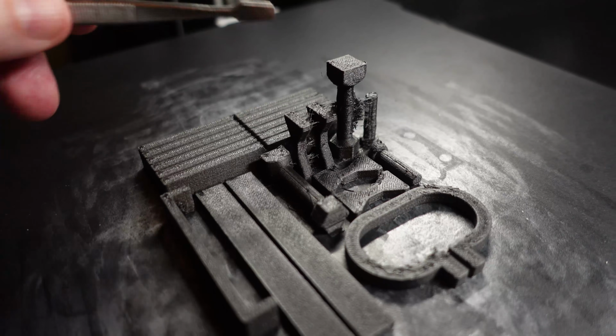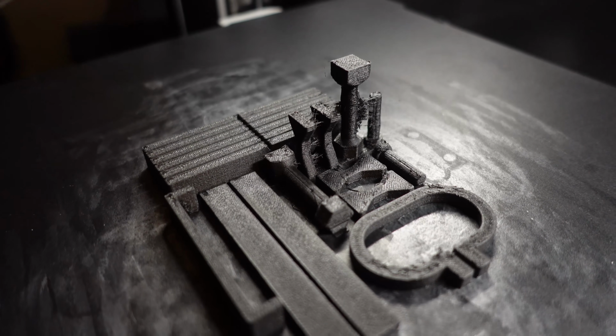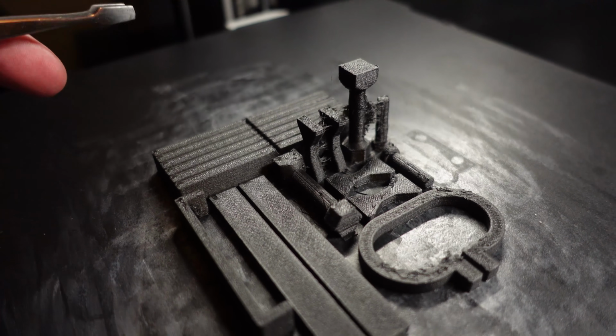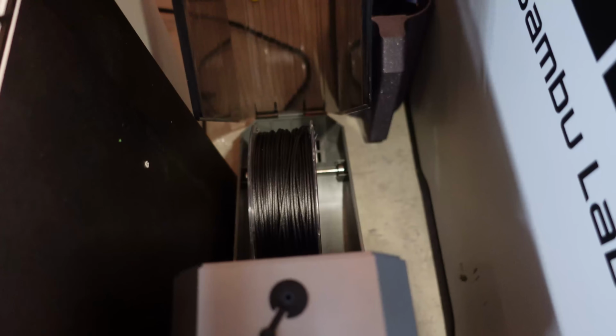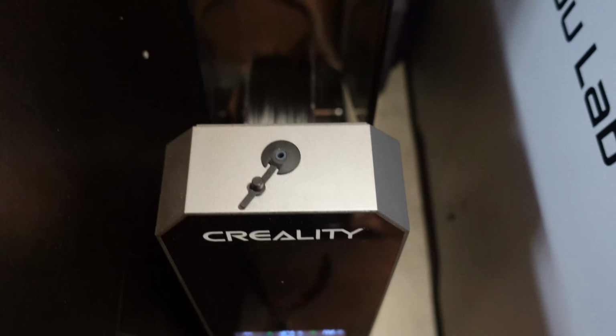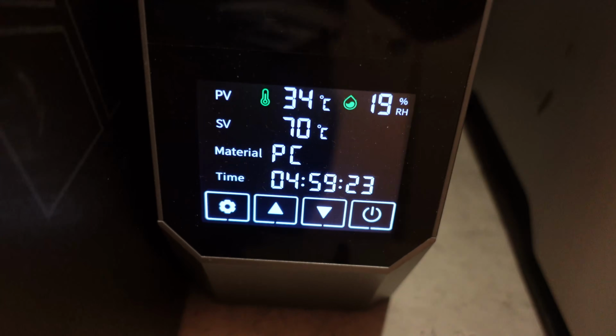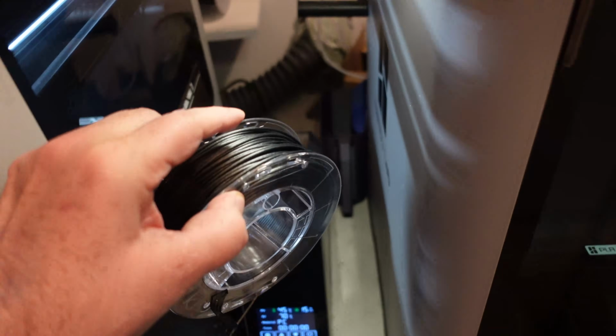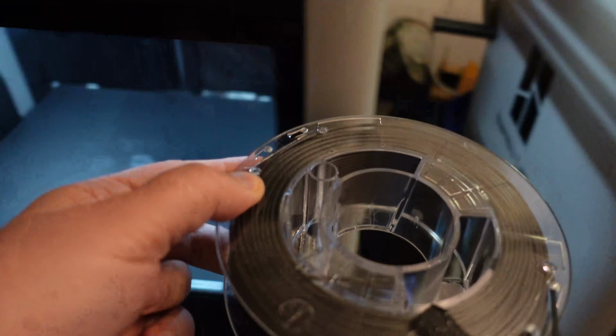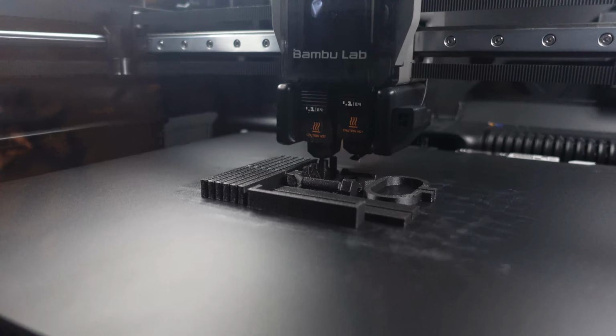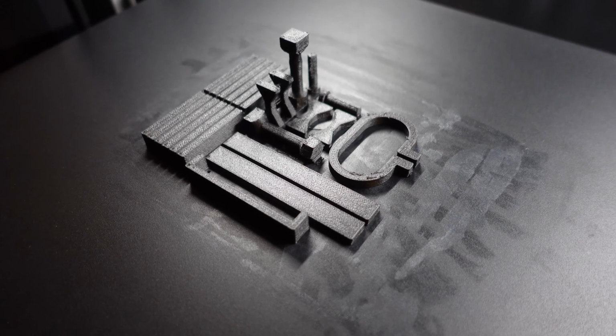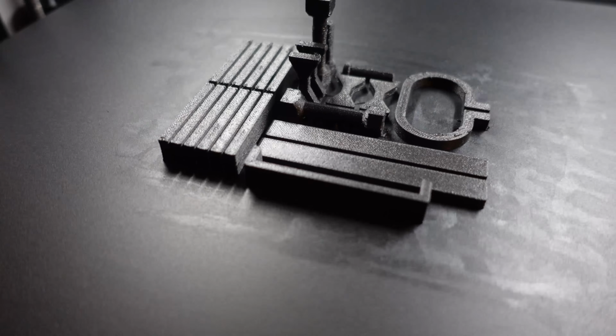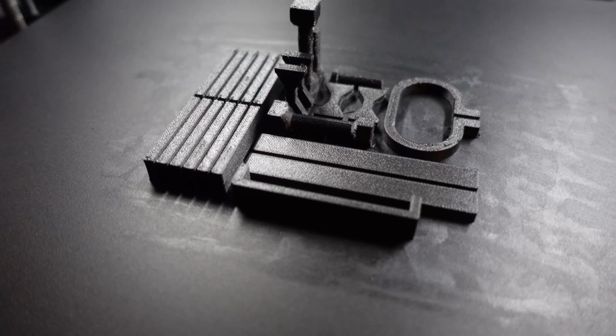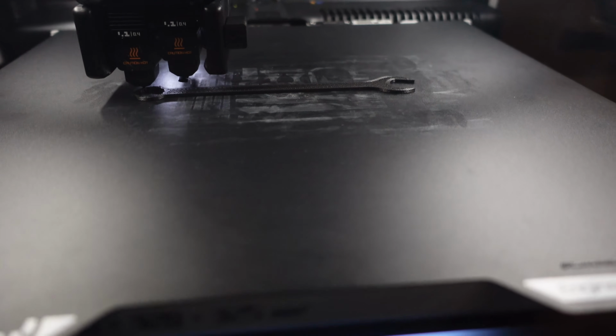I will dry the filament and maybe reprint only these 4, I'm not sure at this moment, because this is a very small spool and I also want to use this filament in the PCCF comparison video. The drying is not easy because this is so small a spool. Total drying time was 8 hours at 70 degrees Celsius. Looks promising so far. Look at this difference. And I think for the first time I will keep both test objects and I will do some comparison of wet versus dry filament. Open end wrench, because I'm preparing a 5 PCCF comparison video and this will be one of the tests.